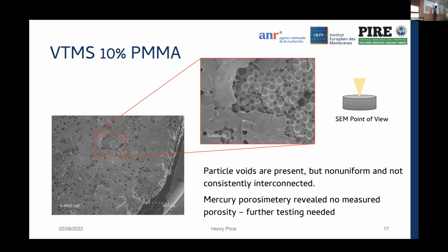But the important thing to note is on this image here, you can see that the distribution of these pores from the PMMA beads is not uniform throughout the sample. You can see in this area here, it's quite concentrated and they are actually touching, but here, they're much more widely spread out. And so this leads to the conclusion that there is not interconnected porosity at these lower weight percentages of PMMA addition.